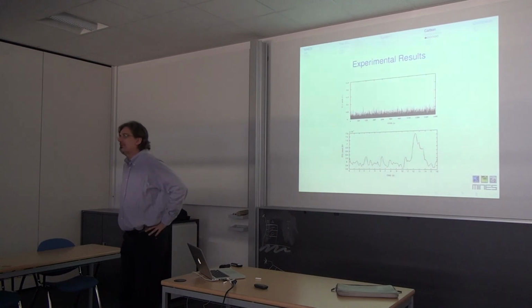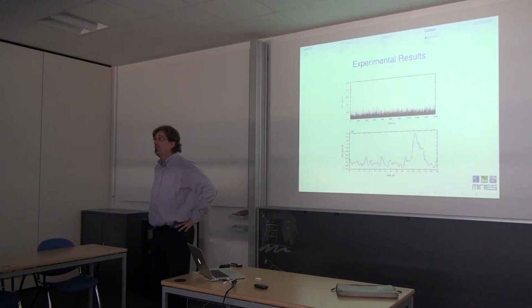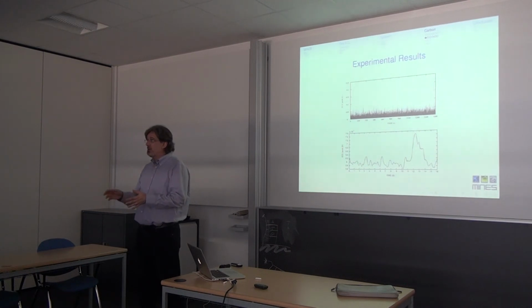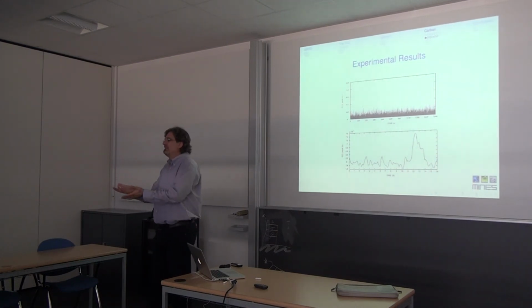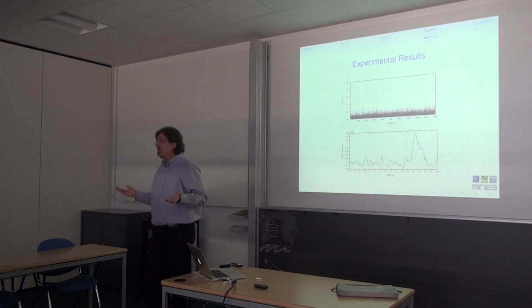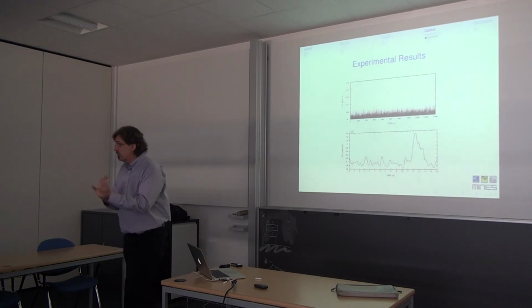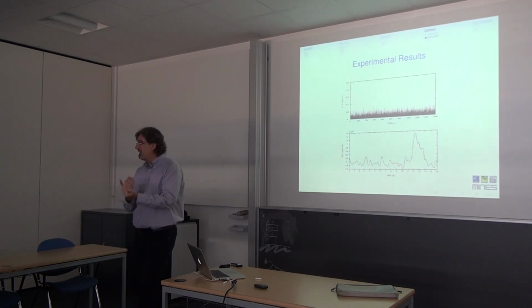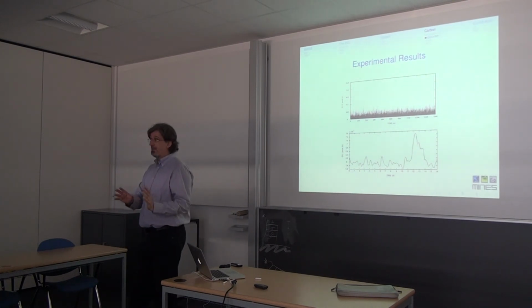No, the difference between the carbon nanotubes is related also to the fact that during the experiment we found pieces of carbon nanotubes around. I did not tell because maybe of course you can improve it, you can increase it, but you have seen the surfaces are very different. So you can say, yes, I can do a sort of dynamic calibration. But at this stage, with these dimensions, you cannot do anything, because it changes every time too much.